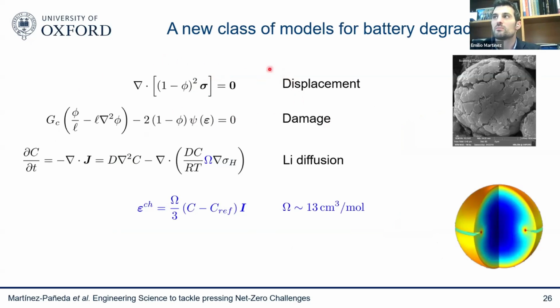And you can see, so you solve a displacement problem. This is basically the standard balance of linear momentum that you were seeing during your undergrad. Then there's an equation for the evolution of the fracture, which again uses one of these phase-field methods that have been a revolution in fracture mechanics, and basically compares the stored energy in your material to the fracture energy. This is the Griffith criterion that you learn about during your undergrad. And then the transport problem. Before it was hydrogen, now it's lithium.